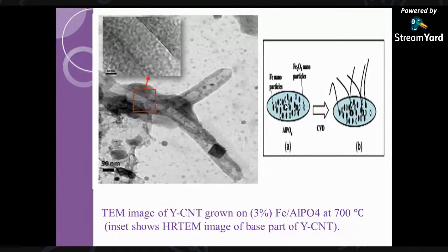We presume that our catalyst, aluminum phosphate, has iron nanoparticles over it, and in addition it has some iron oxide nanoparticles. So we can find two types of species over this catalyst. During the reaction, you can see two nanoparticles with an oxide nanoparticle between them. When you find some barrier between two nanoparticles, two carbon nanotubes come together, and they are creating Y-shaped carbon nanotubes.